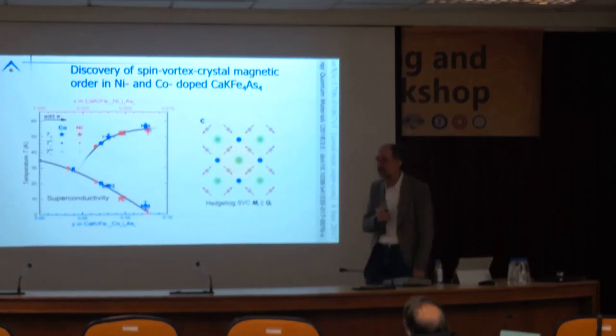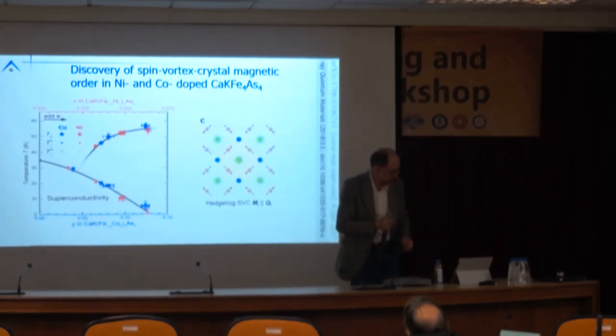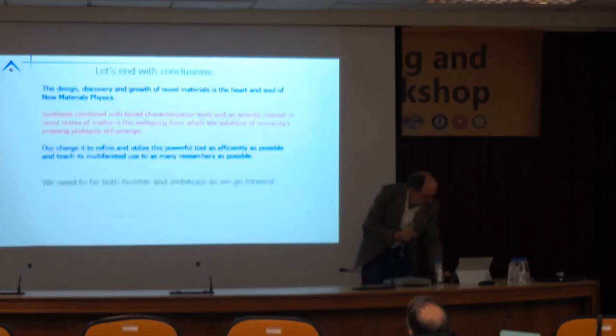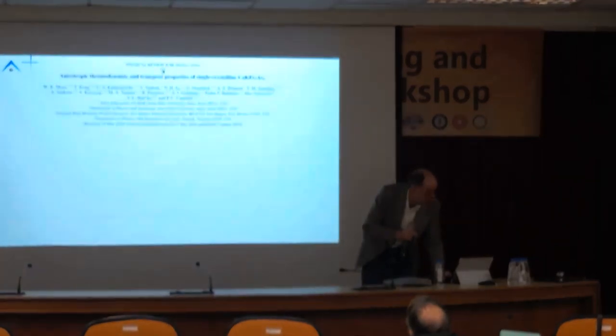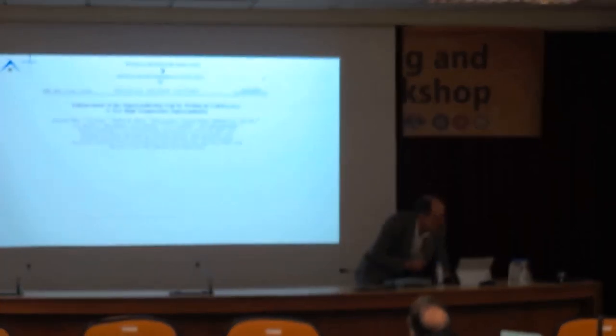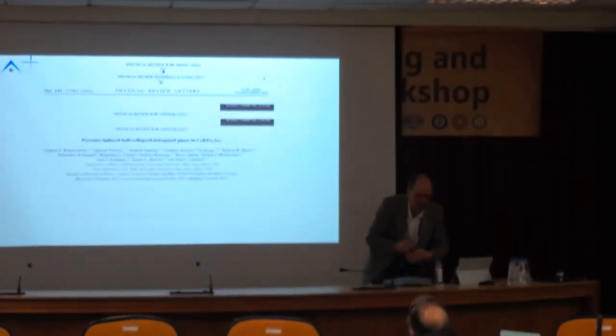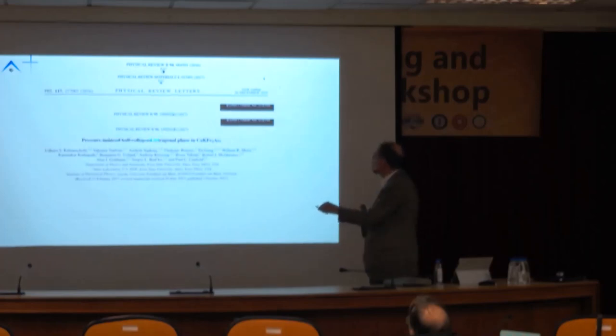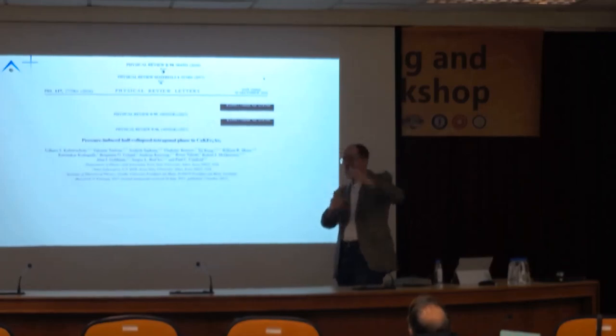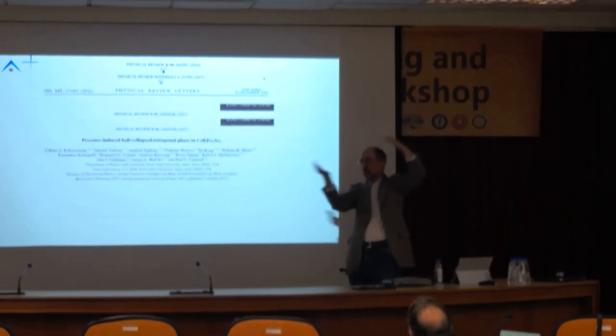And is there any study of these under pressure? Not yet, I moved these to backups, but let's see, under pressure. These materials are really neat. So I've got calcium and potassium. In the calcium ones, you do high pressure, and basically you have the formation of arsenic-arsenic bonding across the calcium layer. That only happens with calcium at low pressure. Here I've got calcium and potassium, and you squeeze on it, the calcium goes first, and we get a half collapse effect. Then we squeeze more, and we get the potassium.